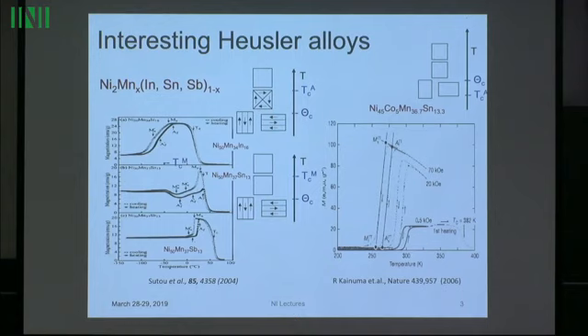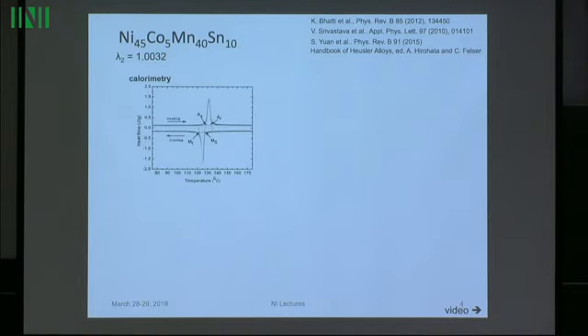However, when you look at this, a former postdoc of mine, Vijay Shrivastava, realized immediately that if that's the case, you should be able to move this TCA above the theta C by also changing composition, because that also moves the wells up and down. So he had some good intuition about how to change the composition of this material to move TCA above, and he got this material. He was also trying to make lambda 2 equal to 1, and this particular alloy has lambda 2 quite close to 1, but there's also room for improvement. So this could be made more reversible, probably by further compositional changes. But anyway, this is the behavior.